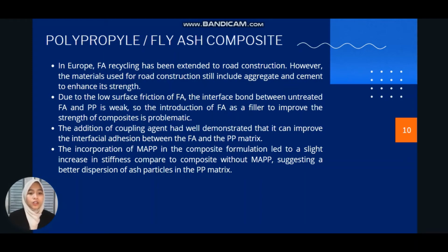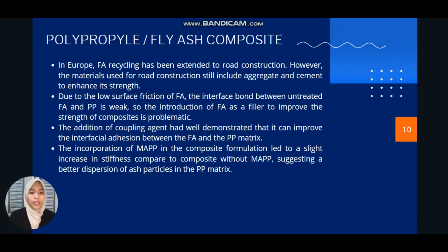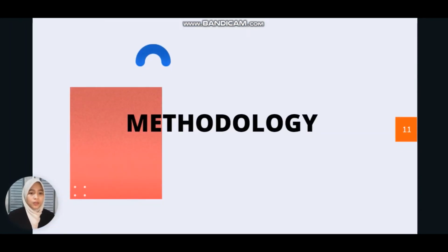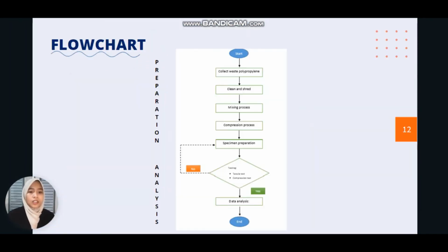So due to the low surface friction of fly ash, the interface bond between untreated FA and PP is weak. So the introduction of FA as a filler to improve the composite is problematic. So in this case, we need a coupling agent to help the dispersion of ash particles in the PP matrix. And next, we will look at the methodology. So this is the flowchart of how we prepare the composite.